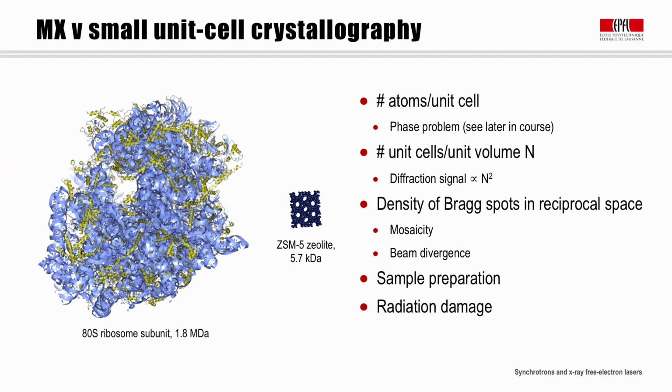Here, it is merely mentioned that this obstacle is further compounded by the fact that, because diffraction peak intensities scale with the square of the number of coherently illuminated unit cells, and because the unit cells in macromolecular crystallography can have linear dimensions up to 2 orders of magnitude larger than those of small inorganic structures, the signal intensity in protein crystallography is concomitantly smaller for a given crystal size.